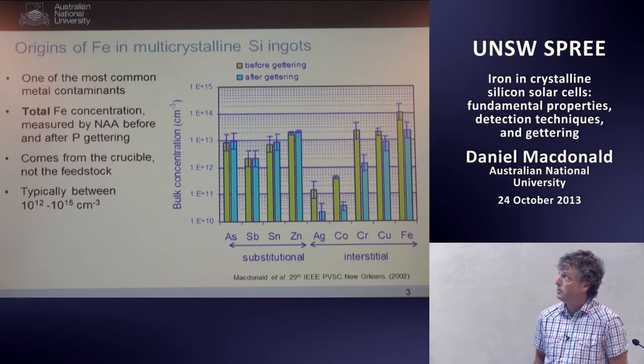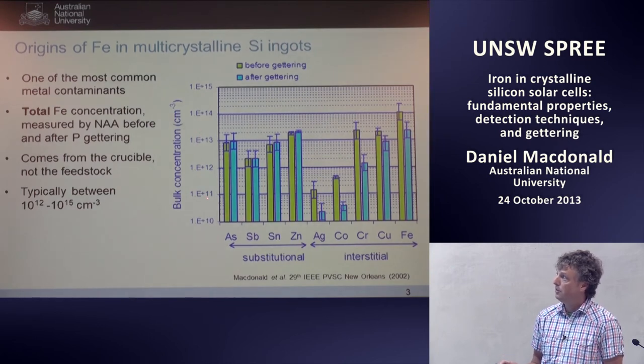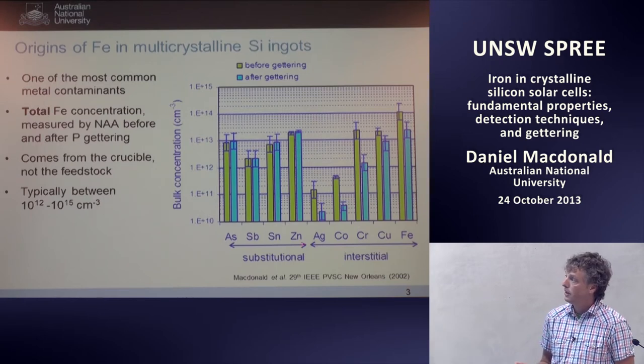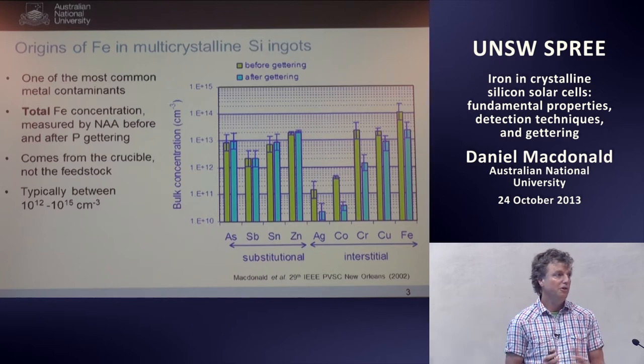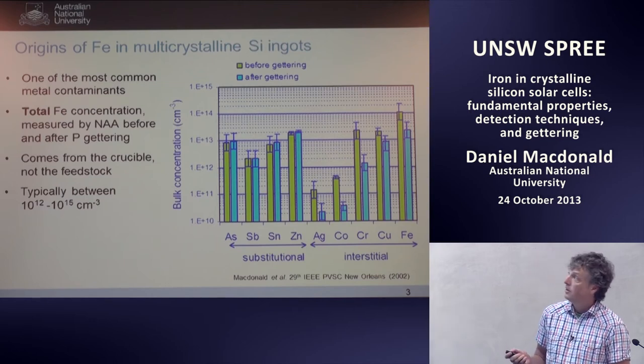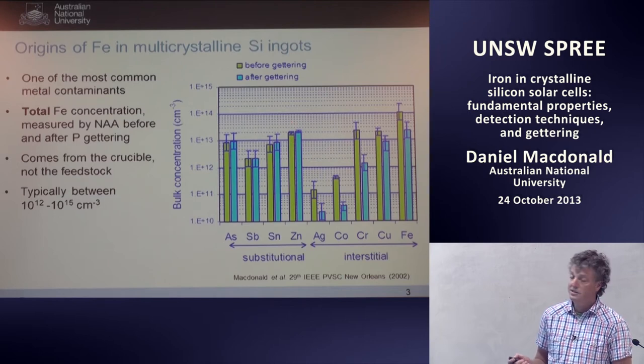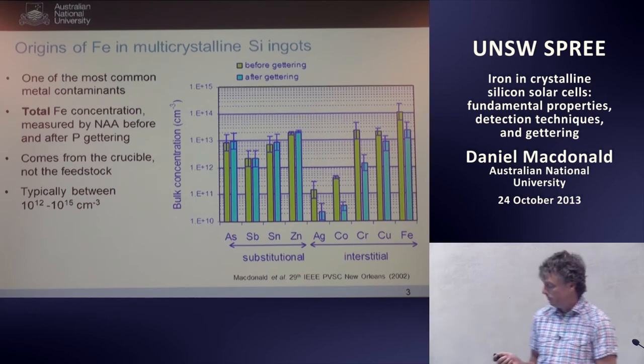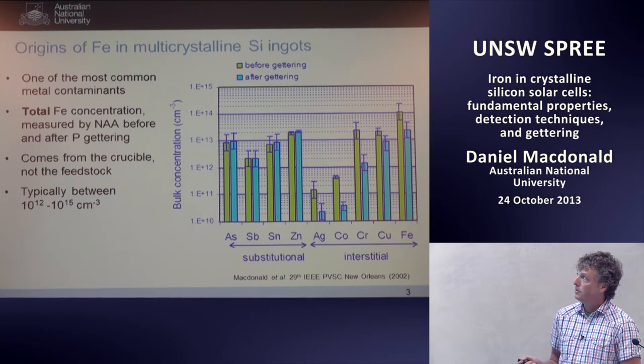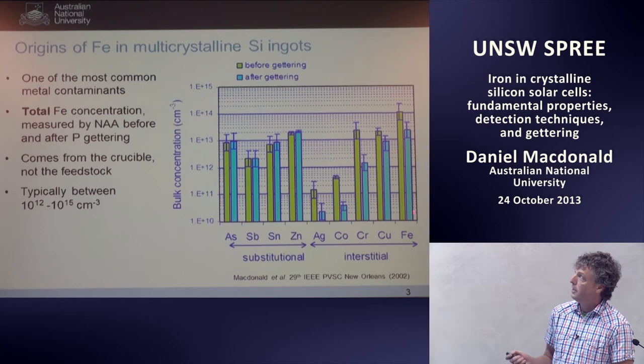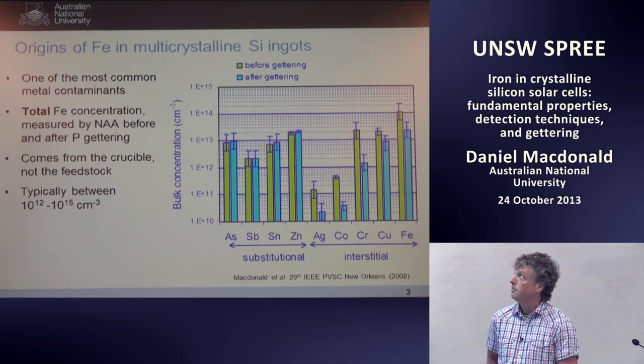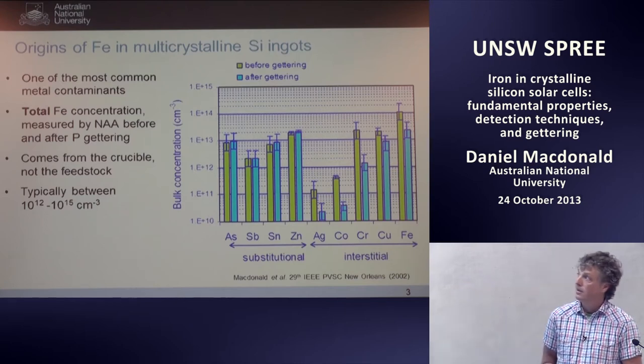Looking at the origins of iron in multicrystalline silicon ingots — this graph shows the concentration of different impurities in a multicrystalline silicon ingot. There's a class of substitutional diffusers which move very slowly, so you can't remove them during a phosphorus diffusion gettering step. For the interstitial diffusers, we see a large drop in concentration after phosphorus gettering. Iron is the most common of those metals both before and after gettering in this multicrystalline ingot. These measurements were performed using neutron activation analysis, detecting the total iron concentration.